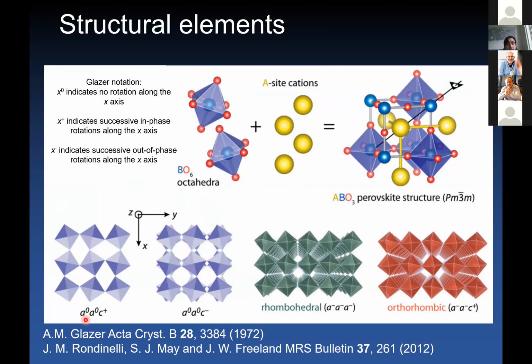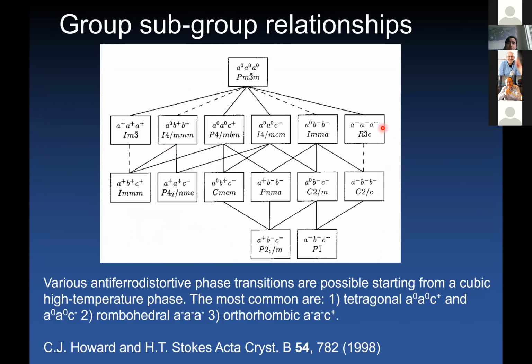Then you can indicate these using this Glazer notation. By X, you indicate the axis of rotation, and 0, plus or minus indicates no rotation, in-phase rotation, or out-of-phase rotations. And the subgroup relationships determine what types of phase transition are symmetry allowed when you cool your system from a high symmetry cubic phase down to a lower temperature, lower symmetry phase. And as I said before, the most common type of transitions are those that bring you either to this rhombohedral a minus, a minus, a minus pattern.